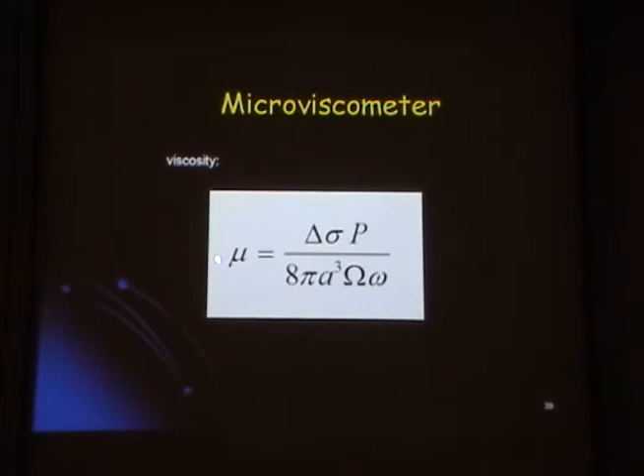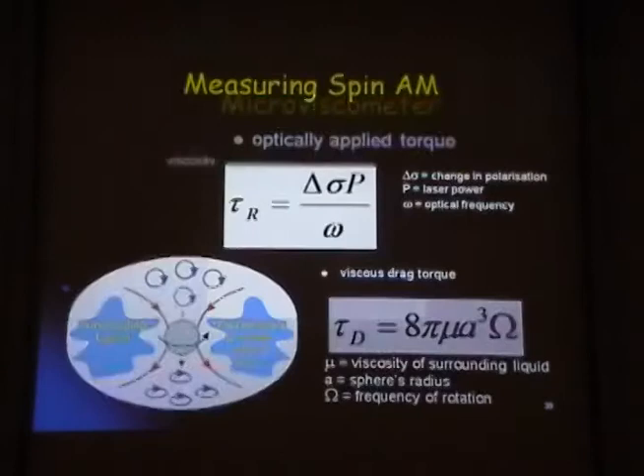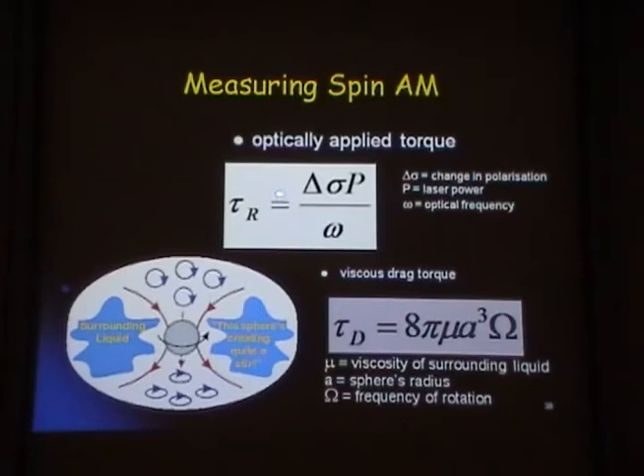and if they do, then I can determine the viscosity. What I'm doing is comparing these two expressions now, optically applied torque to viscous drag torque, they should be equal, so you can see that I can now calculate the viscosity of the liquid, under the assumption that the liquid is only viscous, not viscoelastic. What do I have to have? I have to have a means of measuring frequency of rotation, and I'll show you that. I have to know the size of my particle, under the assumption it's spherical, and measure the change in polarization, which I showed you how to do.